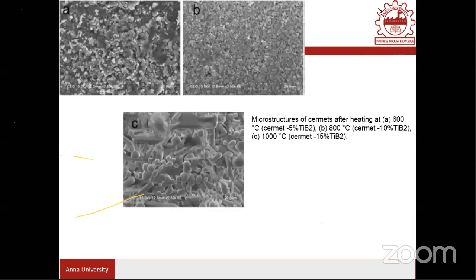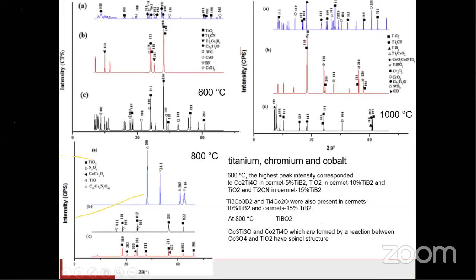If you see the 600 degrees centigrade TiCN, there is not much grain growth, but you can witness a lot of grain growth in the specimen heated to 1000 degrees centigrade. So this would happen in the 5 TiB2 also. I have minimized the number of slides here, and here I have taken 5, 10, 15 TiB2. But in all these conditions, the microstructures look like this. There will be obvious grain growth here, and also one can see a lot of oxide formation. So there is tremendous oxide formation at 1000 degrees centigrade.